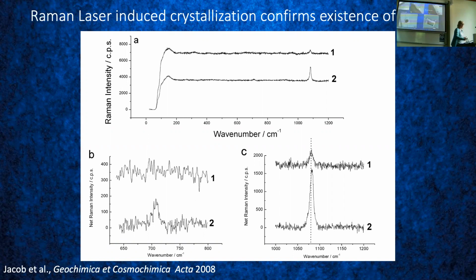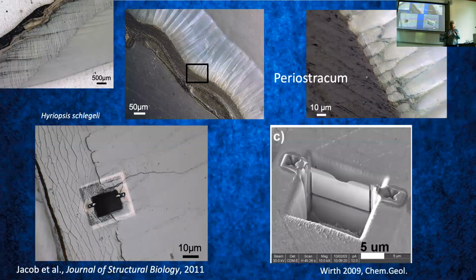So to dive a little bit further into this, we used focused ion beam assisted transmission electron microscopy. I don't know how many of you have done this. We've got this here on campus in CAM. Just as a bit of an explanation, you use the SEM to cut an electron transparent foil out of a very defined area of your sample. Electron transparent foil means the foil is about 150 nanometers in thickness.